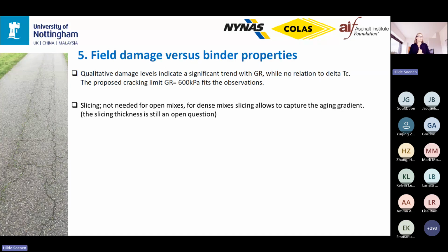So as a conclusion, our qualitative damage levels indicate a significant trend with the Glover-Rowe, while no relation was seen with delta TC, and the proposed cracking limits fit the observations. Slicing would not be needed for open mixes, but for dense mixes, the slicing allows you to capture the gradient, but your value will also depend on your slice thickness. So I will leave that as an open question whether you really need to use this 0.5 centimeter, because that's very thin.